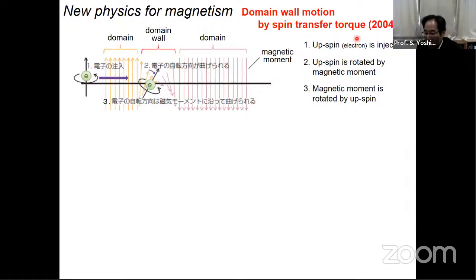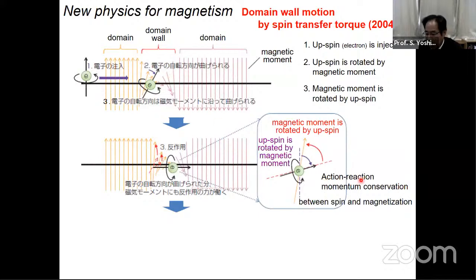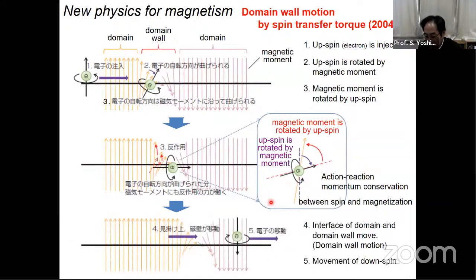Firstly, we inject the up spin from here. Then the up spin is rotated by the magnetic moment, and the magnetic moment is rotated by the up spin. This phenomenon is a kind of action and reaction between spin and magnetization. At that time, the domain wall will move from this position to this position. Finally, the interface of the domain and domain wall moves, and the spin will be turned from up to down. This is the new physics of magnetic domain wall motion by spin transfer torque in 2004.